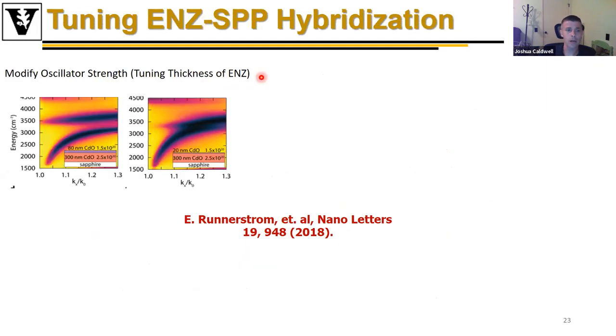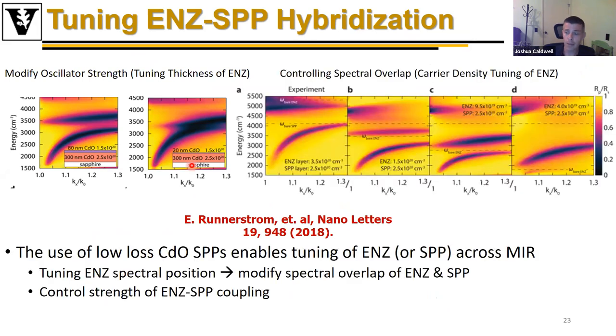Now, we can control the strength of the interaction by, for instance, tuning the oscillator strength of the ENZ layer. Simply by thinning that layer down, I've reduced the number of emitters, if you will, and therefore the strength of that coupling is reduced. You can see here there's almost no splitting between these two modes at 20 nanometer layer thickness. But I can also tune the strength of this coupling by changing the free carrier density of the ENZ layer. As I tune this, I'm transitioning the ENZ dispersion through the plasmonic dispersion. Thus I can dictate where, in spatial coordinates as well as frequency coordinates, that strong coupling occurs.